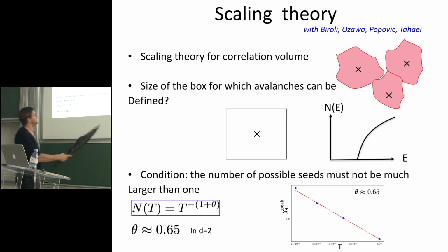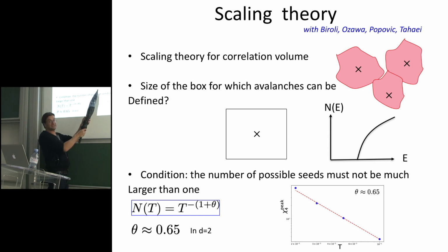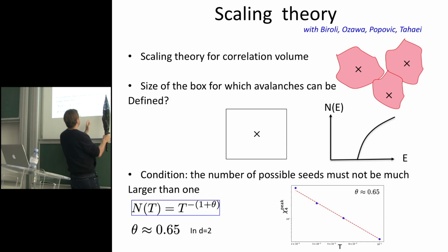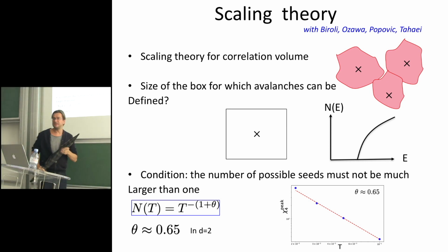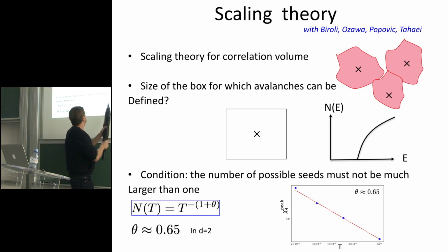So the idea to determine this length scale is asking the following question. If I take a finite size system, at which temperature can I think about avalanche type response? I can think about avalanches if the dynamics is like that: I take the weakest site in my system, it gets activated, then it does its business, it creates a thermal avalanche, then it stops, and then I start a new activated process from here. In this limit, you can really define avalanches. But in your finite box, if the temperature is too large, you cannot think like that because there is competition. There start to be a bunch of states that can nucleate something. So it means there is activity going on in parallel, and you cannot think about avalanches.